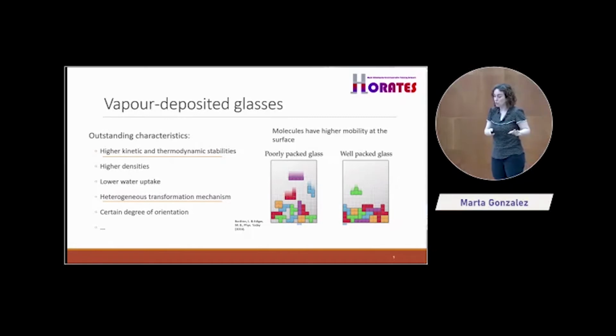Now, before I told you about the stability of glasses, we talked about calorimetry. The thing is that now we're working with thin film glasses. We're talking from, let's say, 20 to 100 to 200 nanometers, something like that, because these are thin films. Okay, you can do microns, but it's not feasible. But we're working with thin films, and we want to study the thermal properties. So where the glass transition was, all the things we were doing with calorimetry, the specific heat. But now we have thin films. And the glass transition, I didn't say that, but this jump that you saw, this peak, is a very low energy peak. The energy involved is very small.